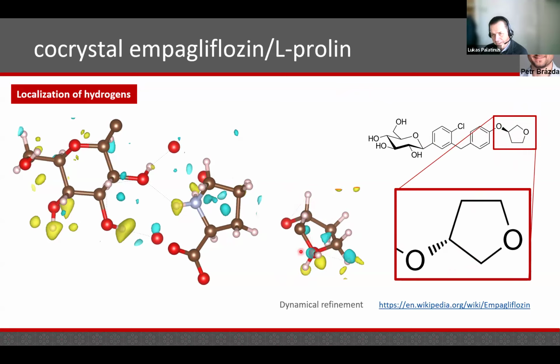So after a little bit of investigation, it turned out that this molecular formula, which came from Wikipedia, was actually wrong. The oxygen should not be here, but here. So not here, but here. And then, of course, this becomes a carbon with two hydrogens, and this becomes an oxygen. But without really seeing these two difference maxima, it would not be so easy to spot that mistake. Nowadays, the Wikipedia entry on empagliflozin is already corrected.